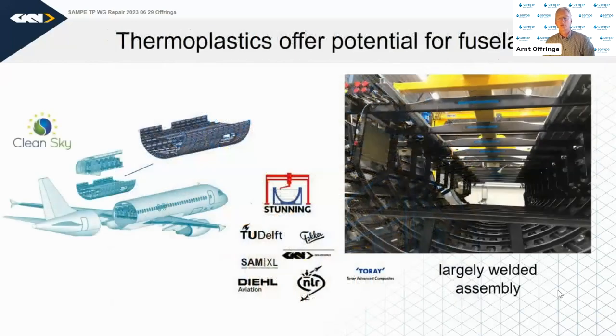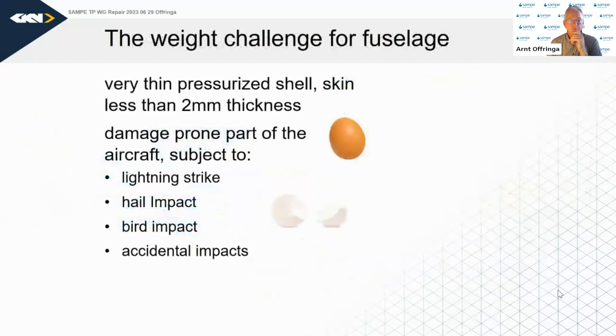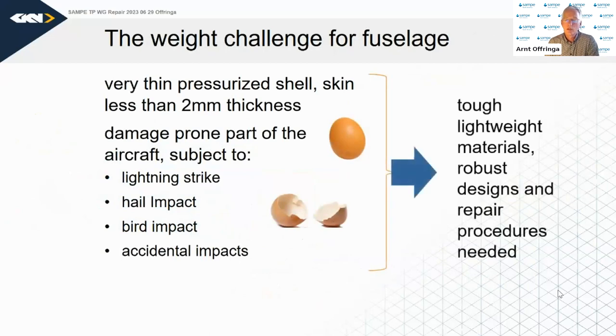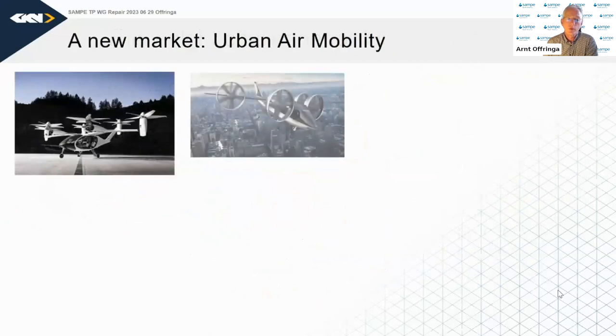And thermoplastic fuselage has been extensively researched, or is being extensively researched, in Clean Sky 2, the European multifunctional fuselage project, with a bottom half and a top half, which will be welded together in Germany later this year. And for fuselage, the challenge in particular is that it is a very thin structure. It's less than 2 millimeters in certain areas. And there are all sorts of damages that can occur, like lightning, hail, bird strike, accidental impacts. So there's a good opportunity here for tough materials with robust designs, and also repair procedures to go with this.